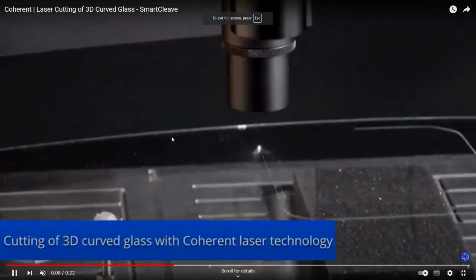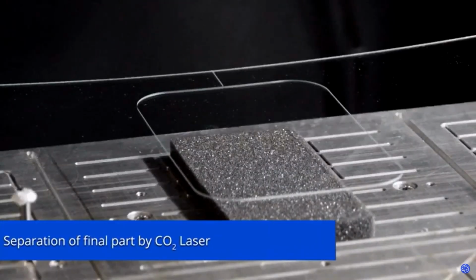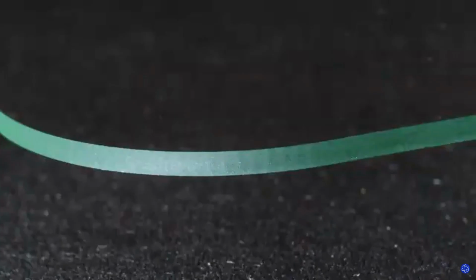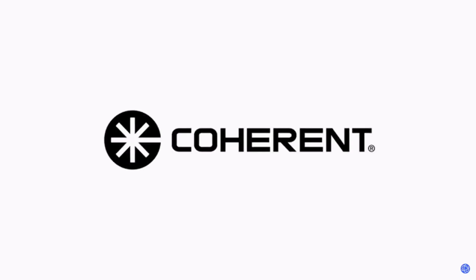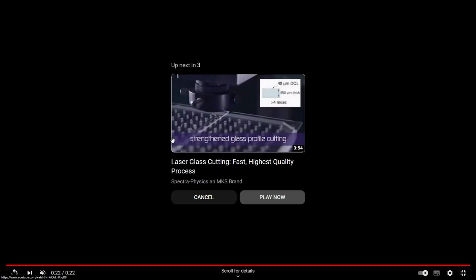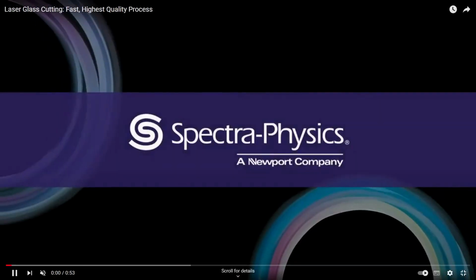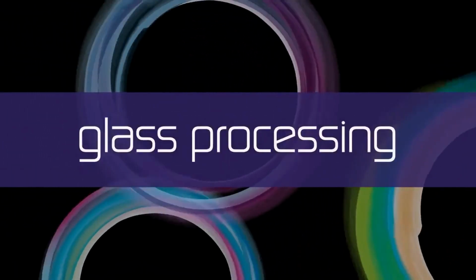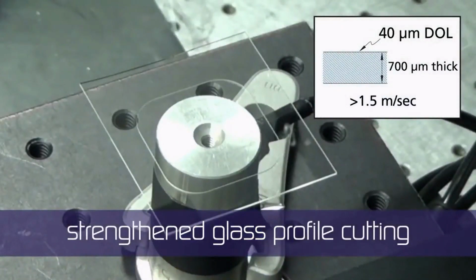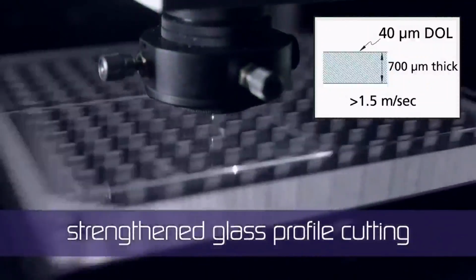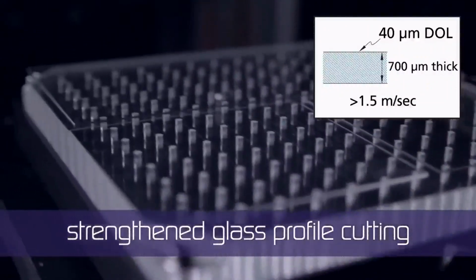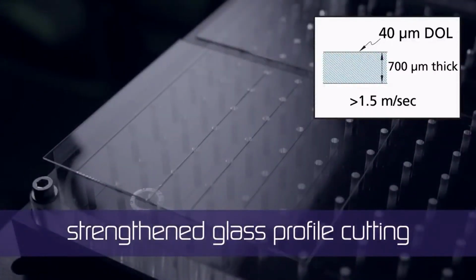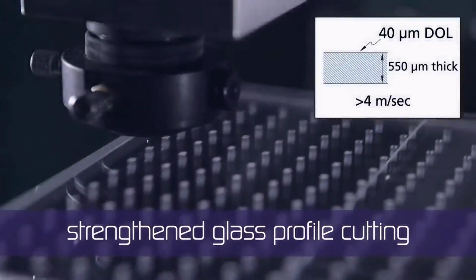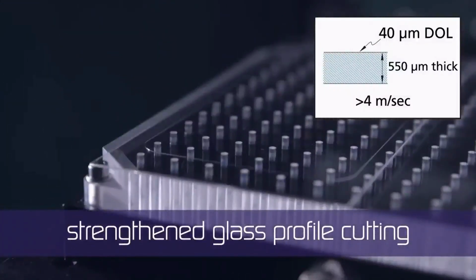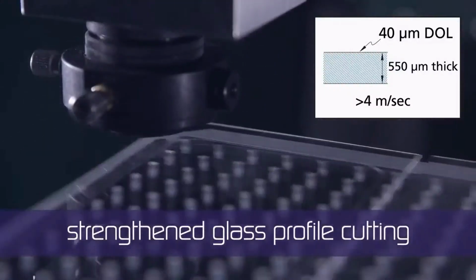Okay. So there are other couple of really niche applications of these ultra-short pulse lasers in advanced manufacturing. This is an example of cutting tempered glass, and this is used in nearly all your mobile phone screens and things like that. The problem with tempered glass is that it tends to want to shatter when you touch it mechanically. And so this is a really neat use of laser dicing, where you can actually cut through the glass from the inside out. And I've got a couple of little examples there. You see that one's a bit sped up, but yeah, so this is focusing the laser inside the transparent material and cutting the glass from the inside out, and it's only really possible with these short pulse lasers with these really high intensities. So this is a really neat technology that's really helped make the mobile phone and the display industry sort of take off as well.